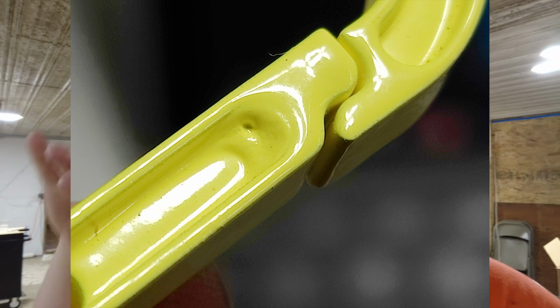The little powder coat particles will just magically stick to your part, and the real beauty of the system is that the particles are insulating. So as they build up in an area, it eliminates that charge. It reduces the attractiveness to the other particles. So the other particles are gonna wanna go find places that are still bare. So to some extent, powder coat is self-leveling, where particles will tend to wanna go to places where the powder is the thinnest. Now in reality, it is still very possible to over powder coat some areas of your part, particularly down in the bottom of pockets.